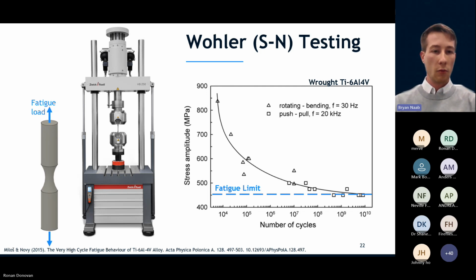And we repeat that for a number of specimens to generate what's called an SN curve. So basically, we're testing different samples at different stress levels. We're generating an SN curve, and based on that, we can estimate the fatigue limit, which is a theoretical limit stress below which we're saying that there's no fatigue occurring. Now, it's of course prudent to add a safety factor to this, just to account for any statistical variation, since fatigue is quite a stochastic phenomenon.